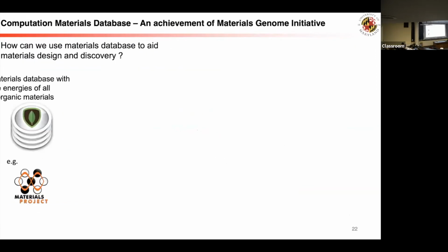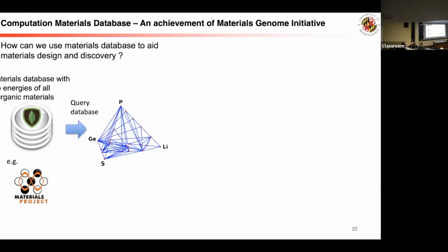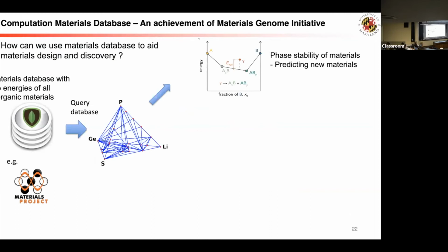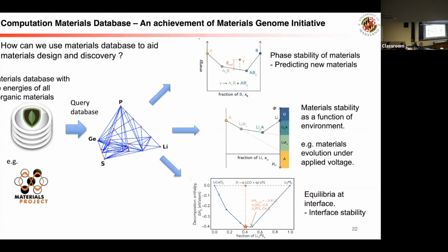The approach we take is to use the materials database that I showed you, because with DFT computation you can simply perform it on all known materials. And once you have it on all materials and put it in a database, that enables you to do a lot of things. For example, once you know all the energies, you can construct a phase diagram, and we can also predict materials phase stability, how material stability changes over chemical potential, the environment.